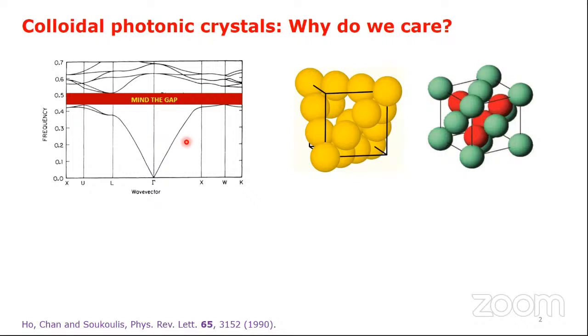If these crystals are built from colloidal particles in the size range of hundreds of nanometers, we can have a platform for visible light management. Self-assembly of designer colloidal particles appeals as a low-cost scalable fabrication route. However, the most sought-after colloidal photonic crystals have rather open structures comprising low-coordinated colloidal particles, making them challenging targets for programmed self-assembly. Additionally, stacking faults in these self-assembled colloidal open crystals tend to compromise their photonic band gaps.